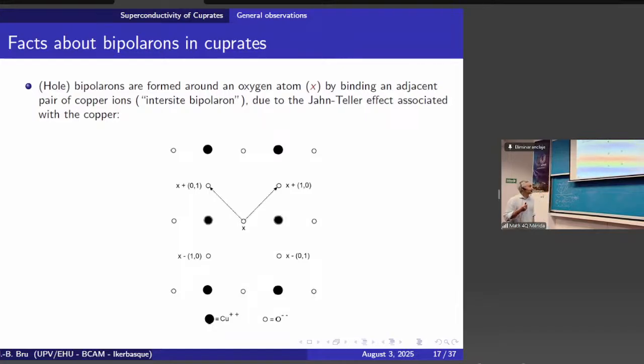And the Jahn-Teller effect, one which has a strong effect, is the copper. So what is the Jahn-Teller effect? You have an electronic structure of the copper which is symmetric. The ground state is symmetric but degenerate, and the degeneracy makes it unstable. And then there is a second, a broken symmetry, which makes a distortion of the state. And then there is a Jahn-Teller effect.